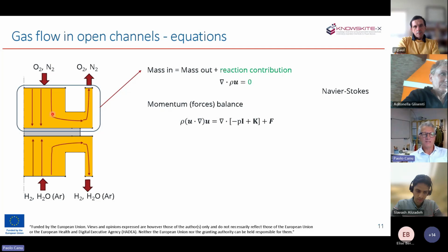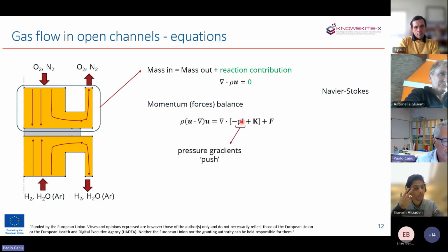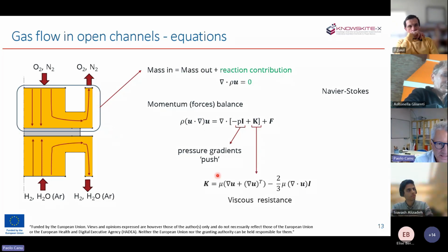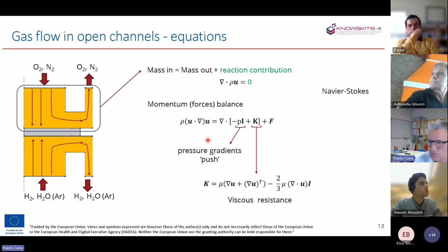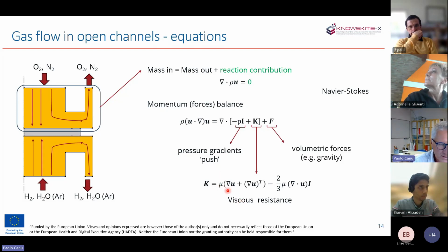Additionally, there's a balance of forces called momentum balance, and this set of equations altogether is called the Navier-Stokes equations, that will tell you the local distribution of velocity. And this includes basically the main driving force for displacement, which is the pressure gradient. So air can flow through this region only if you are pushing from this area. That means there's a pressure higher than on the other side. At the same time, there is some dissipation with the contact with the walls that are normally viscous resistances, so they are dominated by the viscosity. There could also be some volumetric forces, typically gravity, that is normally non-relevant in a pressure flow, and particularly for gases that have a low density.